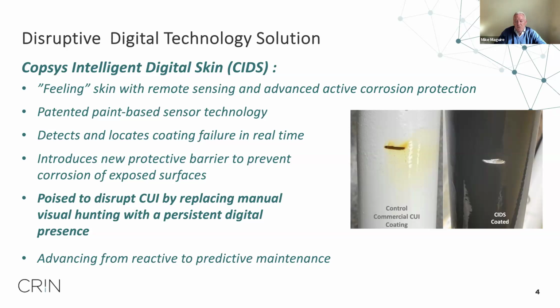And so once the coating fails as your last line of defense, rather than spending time hunting for it, if you had our paint on your pipework, we would be able to alert you at the moment that the coating barrier loss happened. But then we'd also be able to deliver the impressed current cathodic protection or an active electrochemical protection to that location, so that even after the paint was damaged, you wouldn't experience any corrosion.